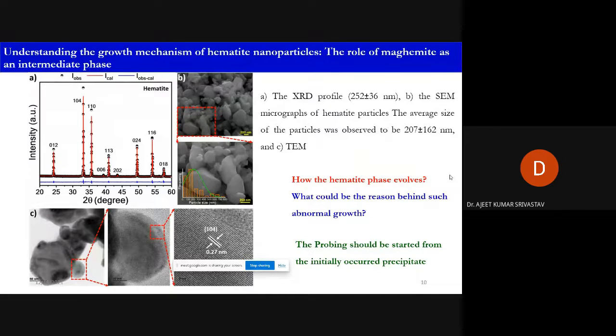And in the XRD profile, we calculate the crystallite size, which is coming almost 250 nanometer. So they are very close, but definitely there is a difference, and this is the difference we are getting due to the different techniques involved in getting the sizes or the distribution. Then we confirm the same from transmission electron microscopy. If you see, we got the variation in the image here, and then we went even for the high resolution lattice fringes, where you can see the confirmation of the phase with the interplanar d-spacing.